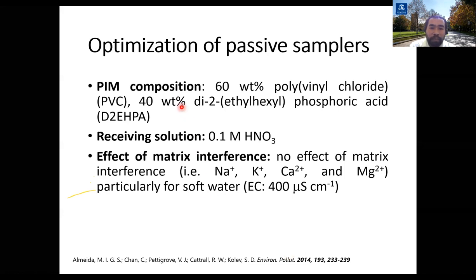So this passive sampling device has been optimized, and the membrane composition used was 60% weight of polyvinyl chloride and 40% di-(2-ethylhexyl) phosphoric acid, which basically acts as a cationic exchanger. And the receiving solution has been optimized to be 0.1 molar nitric acid.